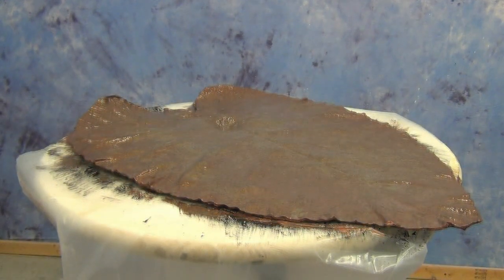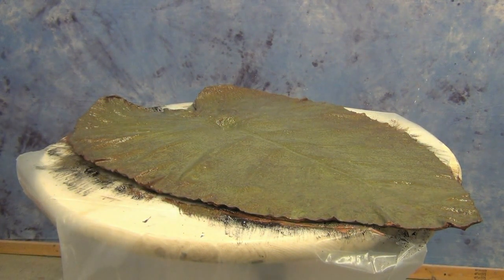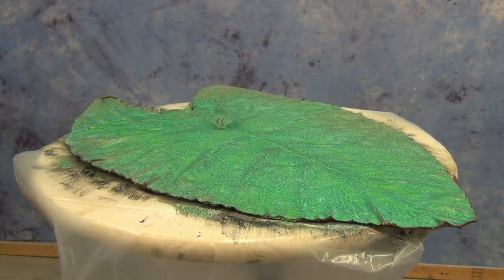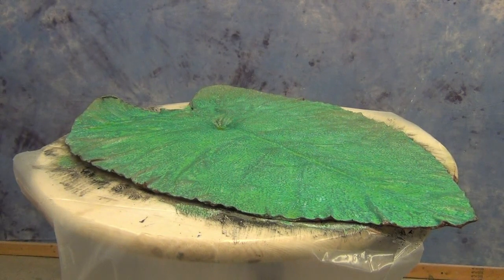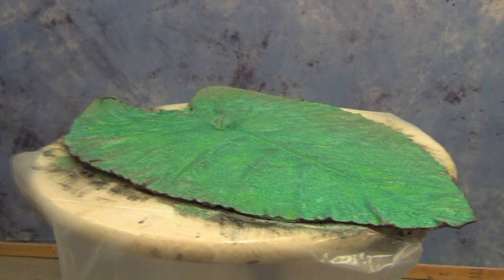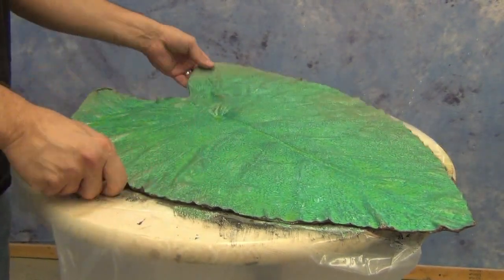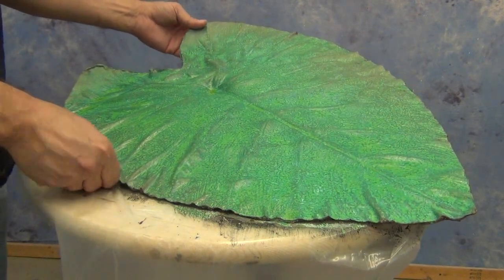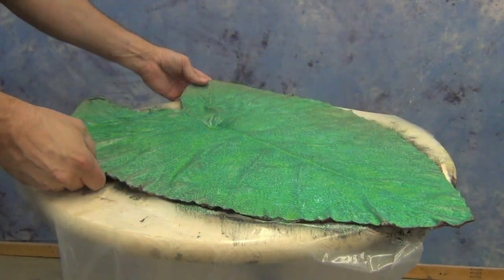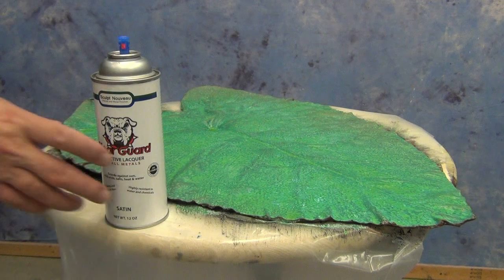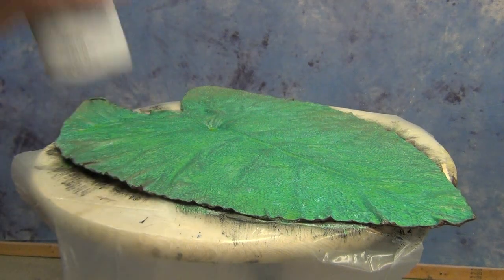And now we're going to see a quick time lapse of that patina developing. And typically this will take a few hours for the color to fully develop. And for the best results, you want a mild temperature and as high of humidity as you can get. Temperatures that are conducive to creating rust will obviously produce good, rich patinas. And this particular color developed in about 6 hours.